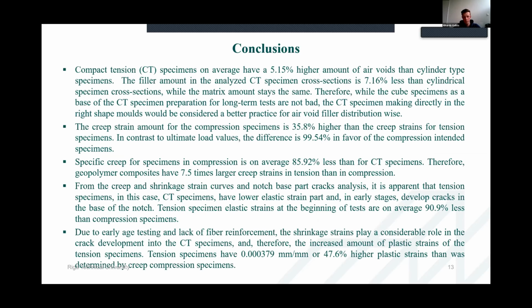So for the conclusions here, we can conclude from these tests that compact tension specimens have a significantly higher amount of air voids than cylinder type specimens, which leads to thinking that a cube-shaped base for making the compact tension specimen is not quite good air-void-wise, because even though the samples were vibrated when they were made into cubes, not all of the air can escape in the vibrating process, and a significant amount of air still remains there.